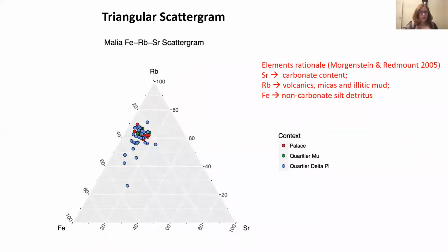These results were further supported by other statistical analysis, such as the Scattergram, which is mapping iron, rubidium, and strontium through a methodology that has been trailblazed by Morgenstein and Redmount in their analysis of mudbrick architecture in Egypt through portable XRF, and is now being widely implemented around the world. In this case, strontium is a proxy for carbonate content, whereas rubidium is a proxy for mica and illitic mud, and iron for the non-carbonate silt detritus. As you can see, also in this graph, the cluster is quite tight, representing the continuity of raw source material.